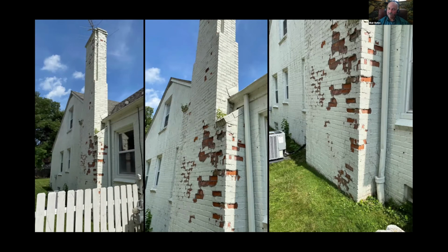If you have a chimney like this, you might want to use an elastomeric coating. It goes on very thick. You can still see the texture of the brick joints, but it's a rubberized paint. You do a detail coat over any cracks, and then you do 2 coats. And it's 50 square feet per gallon is the yield rate to do it properly. But if you're stuck with this, then that's what you end up doing, providing something that's waterproof.